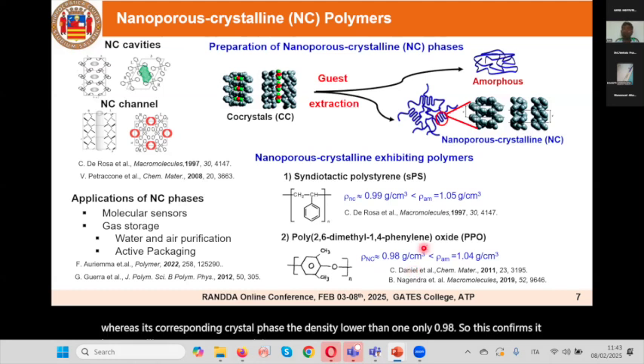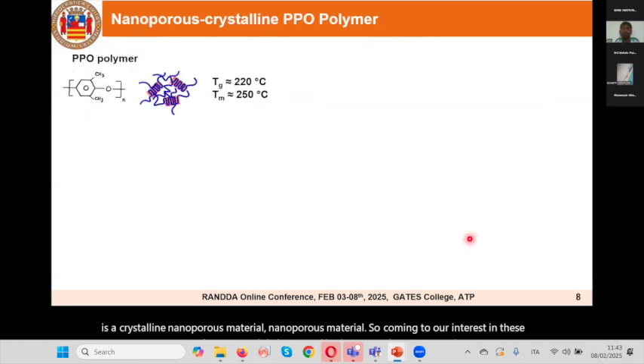Coming to our interest in these two nanoporous materials, we are mainly interested in the PPO polymer because this is a very special polymer. It has very good thermal properties, and Tg and Tm are more than 200 degrees centigrade. Moreover, it is porous in both crystalline and amorphous phases. That's one of the reasons we are mainly interested in PPO. The porosity in the amorphous phase was discovered by Professor Factor in 1969, and the presence of crystalline nanoporosity was recently discovered by Professor Daniel et al. in 2011. So this confirms it is porous in both crystalline and amorphous phases.